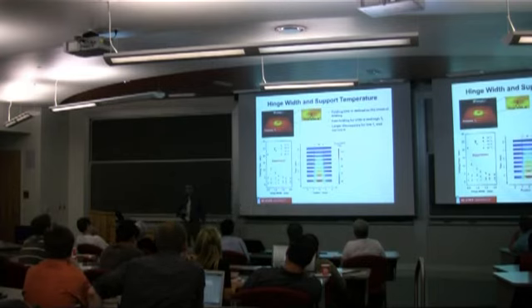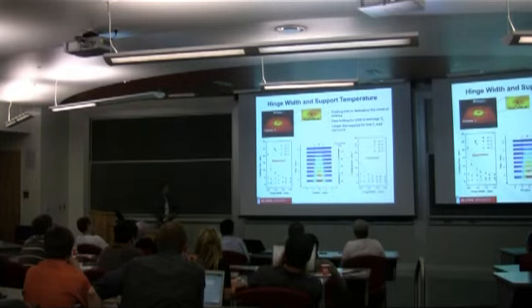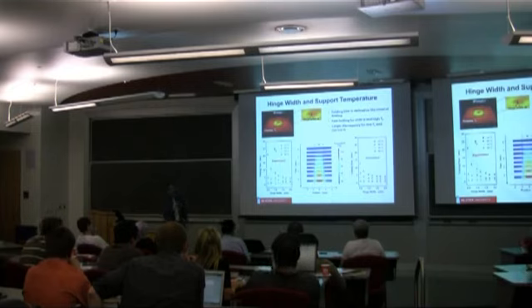And using only one fitting parameter, we model this. And that fitting parameter is the temperature of the surface when we see folding. And our model predicts both qualitatively and quantitatively the experimental trends that we see.